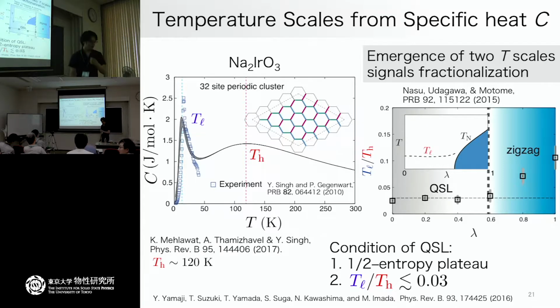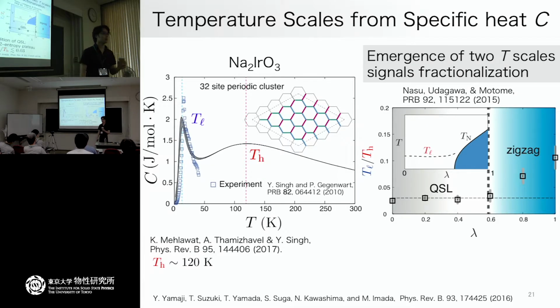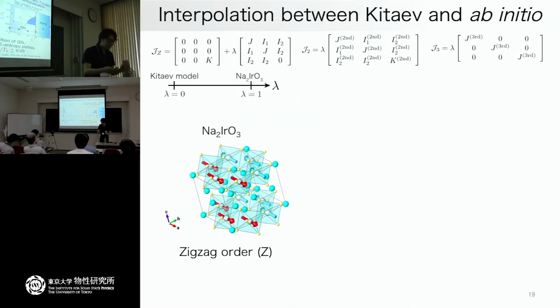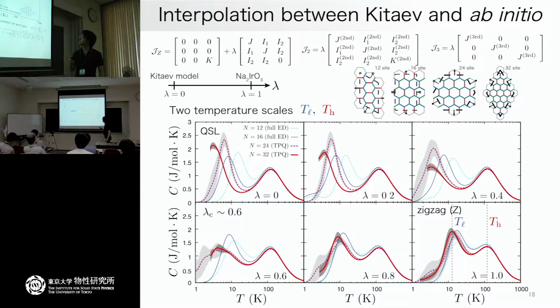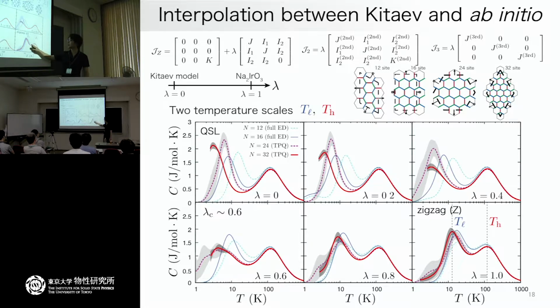Please. How large is the finite size effect? Did you check some? Yes, here we have 32 sites, and this dotted one is a 24 site cluster. And how low is the temperature? It's high enough, and it's already converged. Around 10 Kelvin, the difference is not so large.